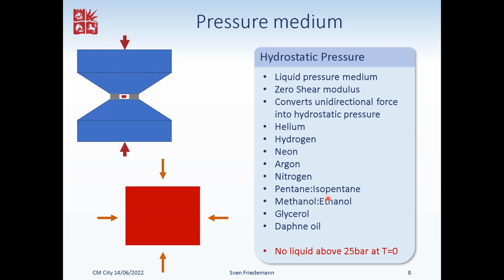So anything will be solid the moment we start to do low temperature experiments, which isn't necessarily a big problem. Helium or even argon is actually quite a soft solid. If you ever try to manipulate solid argon, it feels a bit like butter. It's quite soft. So that means the shear modulus is small, and non-hydrostatic conditions are still quite small. And one can also make sure that one changes pressure only whilst the pressure medium is liquid, such that one avoids squeezing on the sample whilst the pressure medium is solid. Nevertheless, sometimes